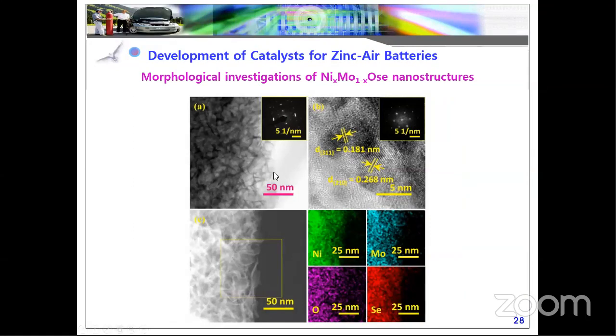The catalyst should be further studied for intrinsic morphology by TEM. From the TEM analysis, you can see the ultrathin nanosheets and wrinkled nanotubes, and the high resolution TEM confirms the high crystallinity. The FFT patterns also confirm the hexagonal shapes of the nanosheets, because this phase matches the hexagonal shapes, and the highly polycrystalline nature is confirmed by SAED patterns, and STEM EDS analysis further confirms the ultrathin and brighter areas.